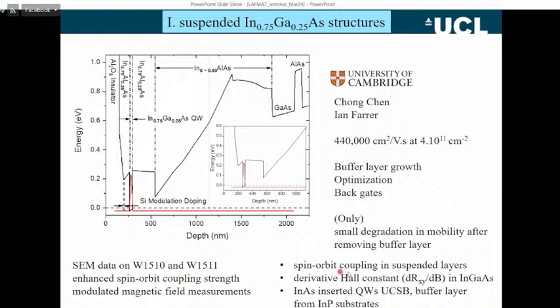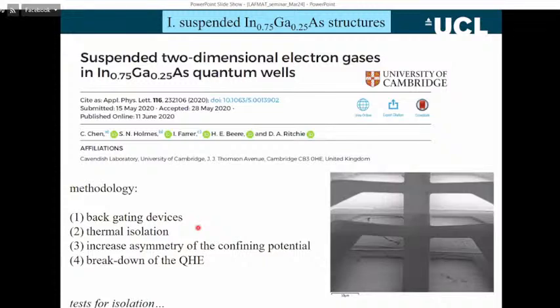So we can then look at this spin-orbit coupling effect electrically in these suspended layers. We're also measuring the Hall effect, where there is actually a lot of structure. We can also try and improve the mobilities in this system. We can insert very, very thin quantum wells that have different spin g-factors, different spin properties. Okay. So some of this work we published. Chong Chen and I did this work in 2020.